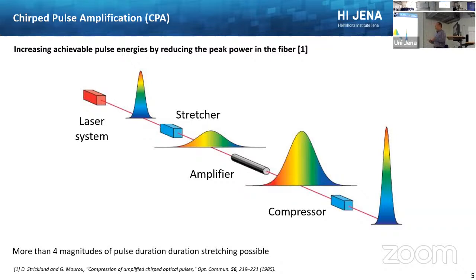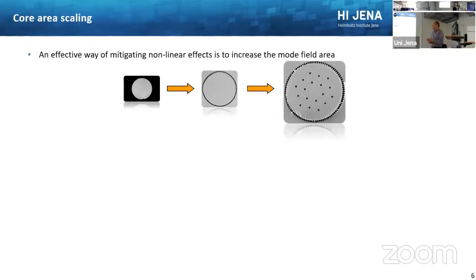What you can now do is to add a stretcher, which is basically a dispersive medium, often built on diffraction gratings, which introduces a chirp or dispersion to your pulse. This means that you stretch the pulse in time, and this reduces your peak intensity and peak power. Then you can amplify it in your amplifier, and afterwards, you can recompress it. In our systems, we regularly stretch the pulses by more than 4 orders of magnitude, from femtosecond up to the nanosecond regime, and can thus also gain about 4 orders of magnitude in power or energy per pulse. So this is the first way to make this usable for ultra-short pulses.